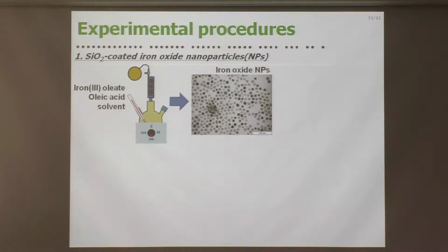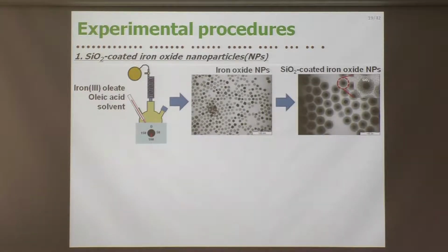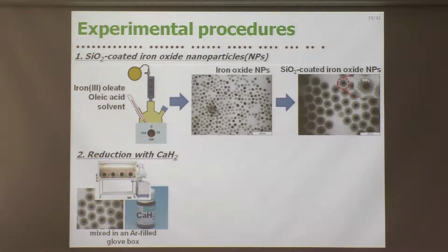Then we coat the surface of the nanoparticles with SiO2. As this expanded view shows, the black spot is the iron oxide nanoparticle, and the surrounding gray shell is the SiO2. So now we have the iron oxide nanoparticles coated with silica.